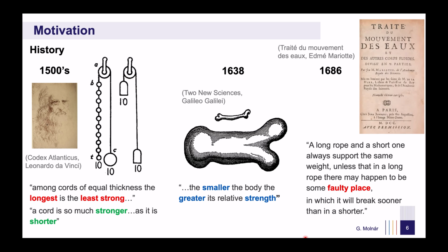It took another 50 years for Mariotte to propose a theory. He suggested that the larger the structure, the higher the probability of finding a large defect. Importantly, he clarified that the intrinsic strength of a material does not decrease, but rather the presence of the defect reduces the observed resistance.